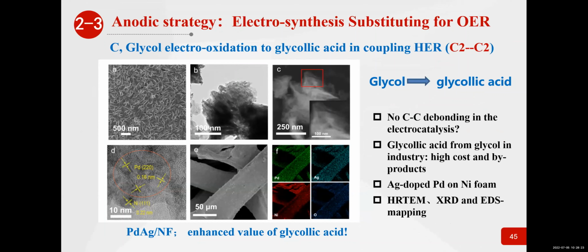And then we can see that the above electrocatalytic process oxidizes glycerol to formate. It is from C3 to C1. It is possible to realize electrosynthesis without carbon-carbon bond breakage. That means it is possible to go from C3 to C3 or from C2 to C2 without breakage of the carbon-carbon bonds. Here, for example, we synthesized a kind of noble metal alloy, palladium and silver alloy loaded on nickel foam. And we realize oxidation of glycol to glycolic acid without the carbon-carbon bond breakage.